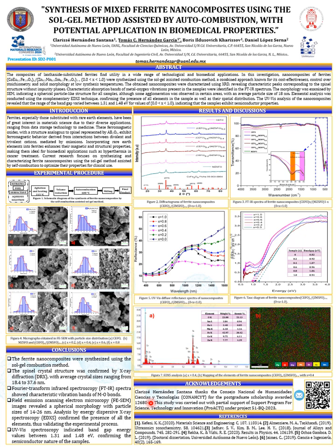Conclusions: the ferrite nanocomposites were synthesized using the sol-gel combustion method. The spinel crystal structure was confirmed by X-ray diffraction, XRD, with average crystal sizes ranging from 18.4 to 37.6 nanometers. Fourier transform infrared spectroscopy, FTIR, spectra showed vibrational bands characteristic of M-O bonds. Field emission scanning electron microscopy, FESEM, images revealed a spherical morphology with particle sizes ranging from 14 to 26 nanometers.